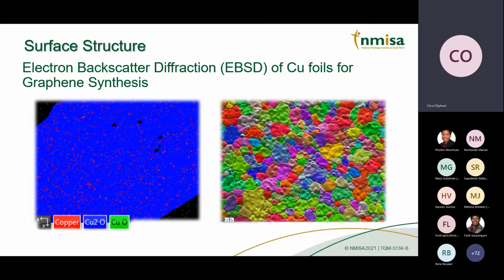It looks like sweets, but it's just grains. And these grains are all color-coded to show their orientation. These grain boundaries, the grain orientation, and the size, all of that influence the synthesis of graphene. So this technique is quite vital for industry to use to grow their graphene sheets.